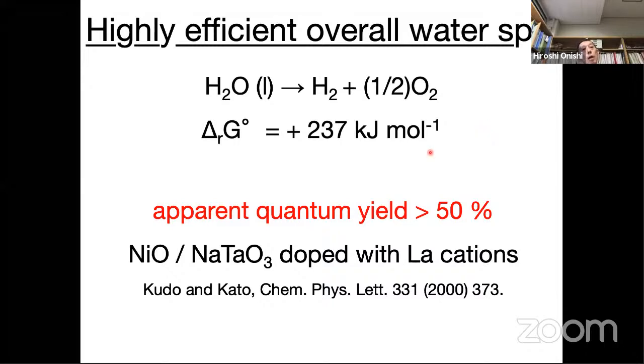Sodium tantalate. This is an inorganic ceramic containing sodium, tantalum, and oxygen. And this is a very good photocatalyst invented by Professor Kudo and co-workers 20 years ago. This is now a well-known photocatalyst. And by using this, the apparent quantum yield of this water splitting reaction exceeded 50%.